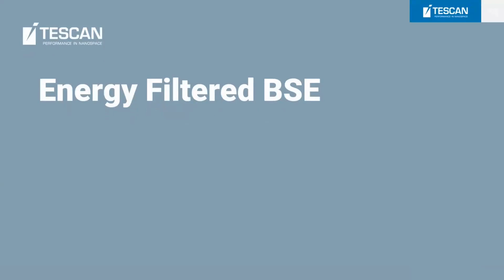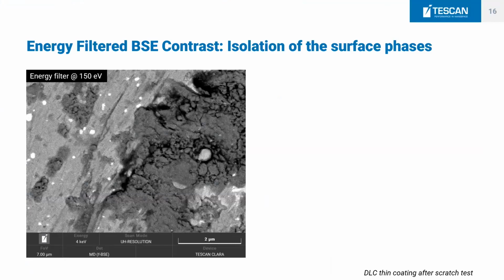So I wanted to mention the energy filtering because it's A, super exciting to see the images, and B, it's also easy to explain and super relevant to what we could do. So this is the typical backscattered electron image of the phase of the material after a scratch test. If you have a material with a tiny coating on it, you apply a scratch test, and you would want to see how much of the material adhered to the substrate, right? And on this image, whatever is dark, you would say it's the coating layer, and whatever has different contrast, so a little bit whiter or brighter, it's the substrate. And you would calculate a percentage, and you would say, well, it was pre-resistant or so.